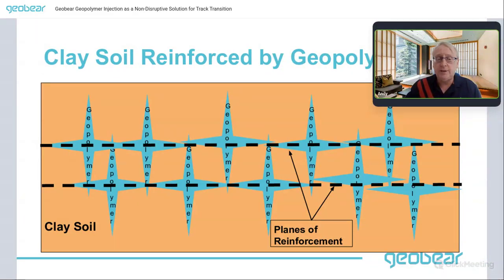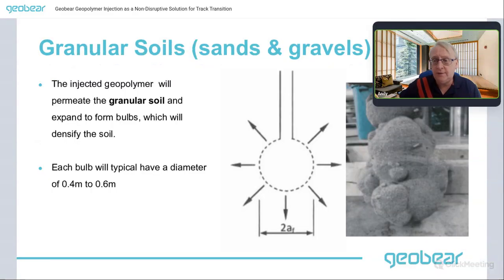If you imagine a line of geopolymer injections in clay which form these fractures, and you arrange them in layers and in lines, you build up a network of reinforcement planes through the clay. This is really how it works. You generate these layers in 3 dimensions of reinforcement within the clay. That's how you end up with a higher bearing capacity and a higher stiffness. Now, in granular soils, the process is slightly different. Injected geopolymer will permeate through the pore space, forming what we call a bulb, and then that bulb will expand.